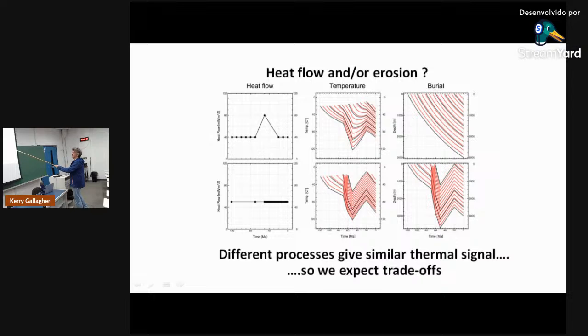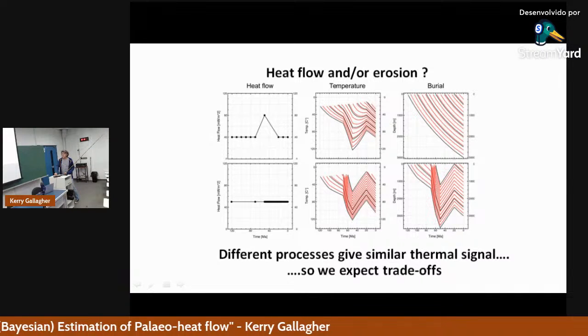Maybe the data can tell us something about the magnitude of that and the timing. But similarly, down the bottom is a model where the heat flow is constant over time. And we just have a period where we have extra burial and then erosion. So things get hot and then get cold again, but that produces much the same effect. And so the question is, can we tell the difference from the data? It's going to be difficult because they have a similar thermal effect. And so what we'd expect to measure in the calibration data that are sensitive to temperature, we'd expect to see much the same thing.